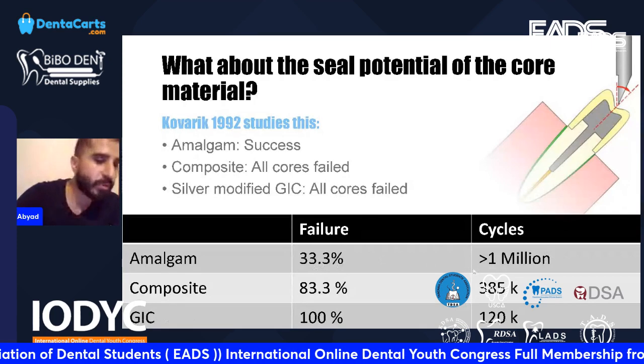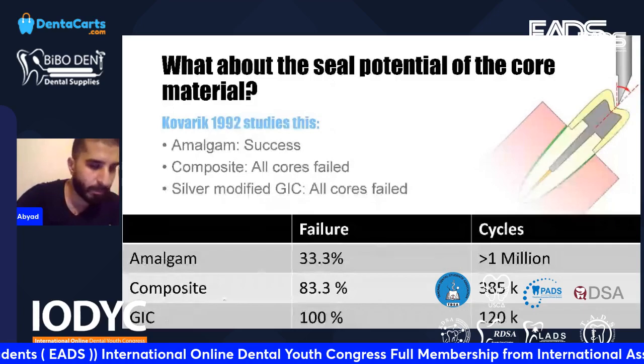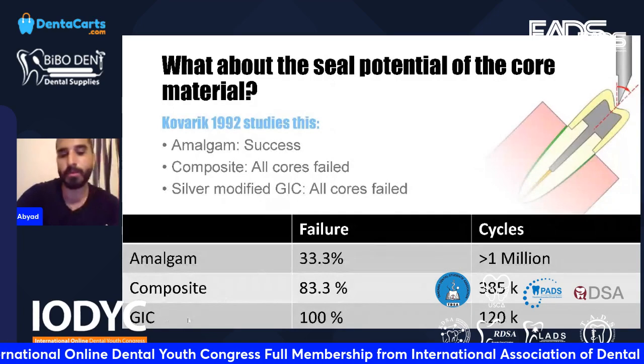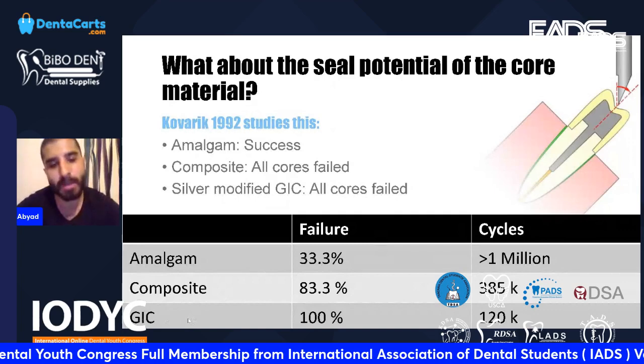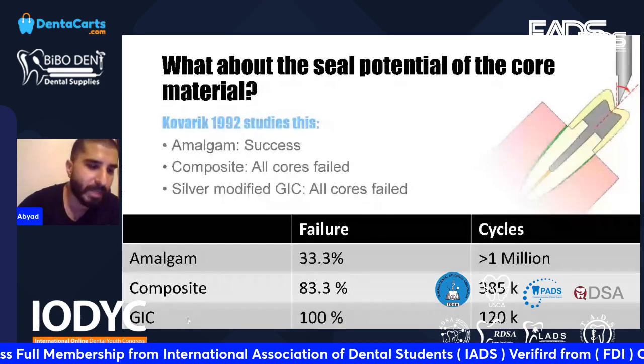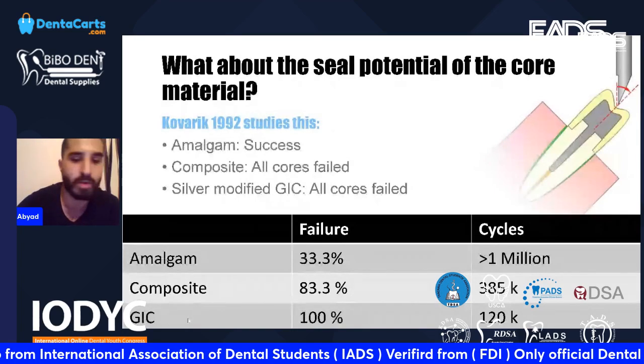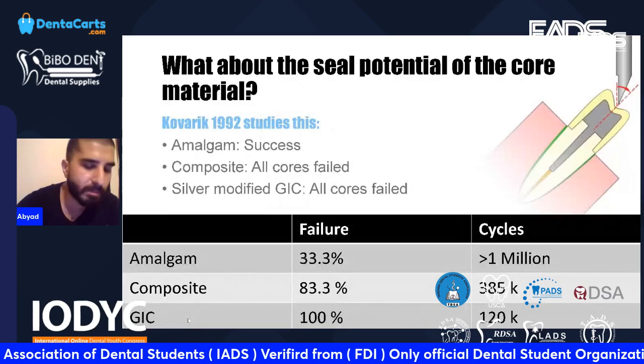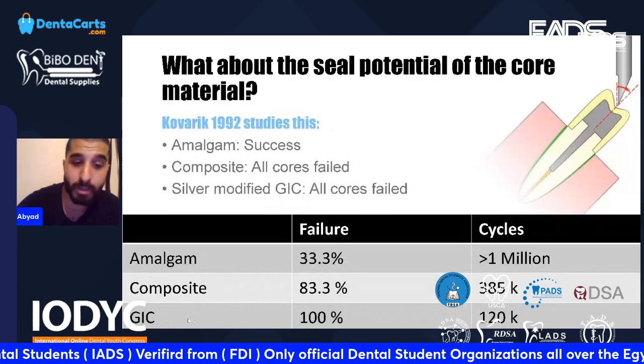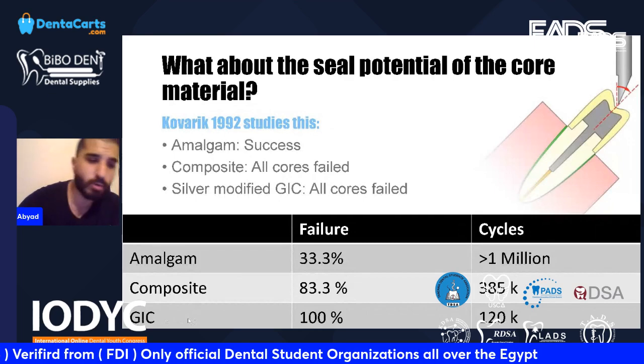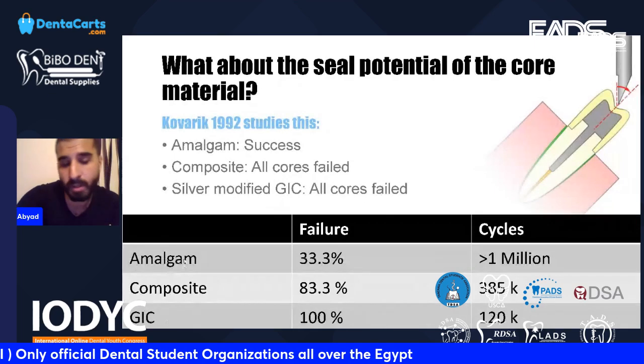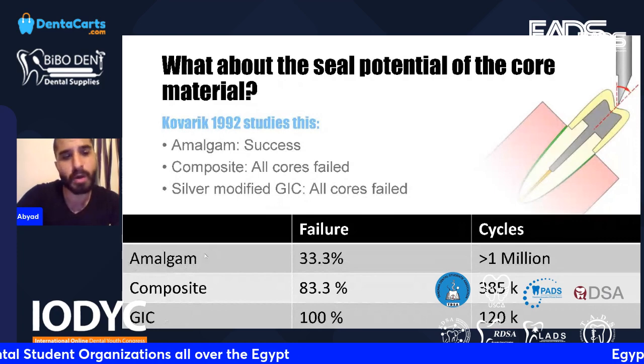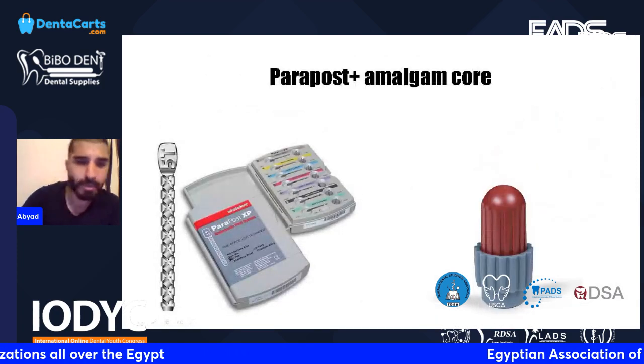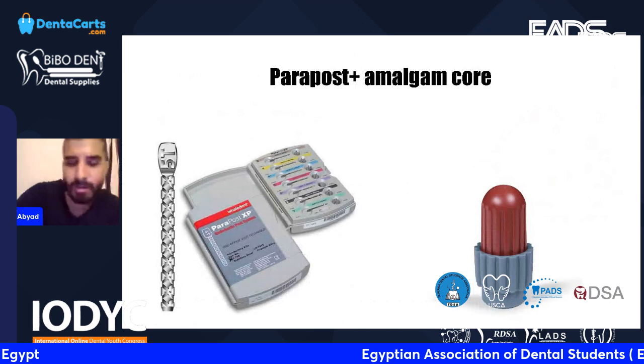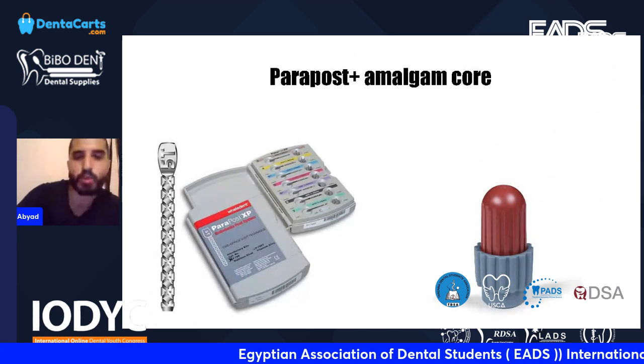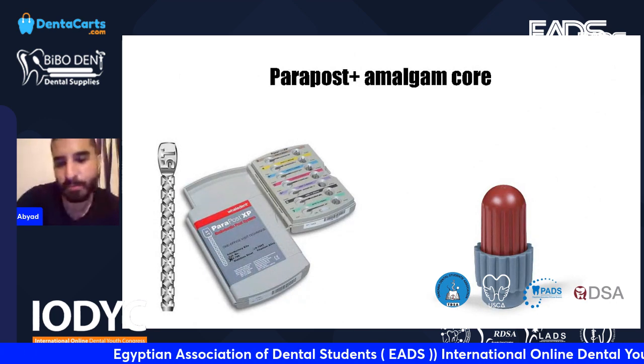So this shows that your amalgam core is much better than the composite core, much better than the glass ionomer core. In essence, that goes back to the nature of the material. It has nothing to do with whether it's amalgam or composite or how it's placed. Metals are simply better at handling fatigue when compared to composites. So you would expect the same behavior of a casted post and core. And that's why I believe that the ultimate posterior post and core system is the parapost system.